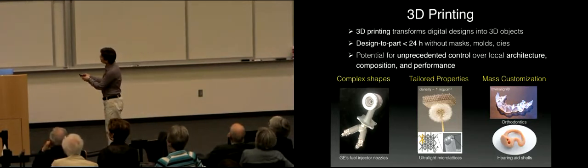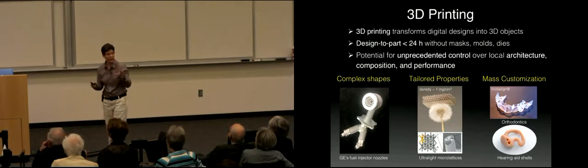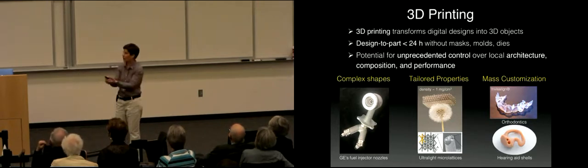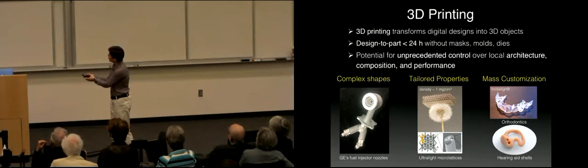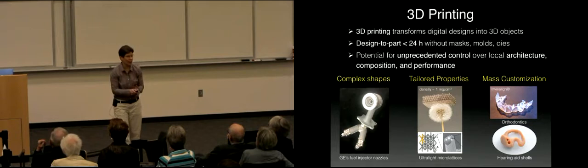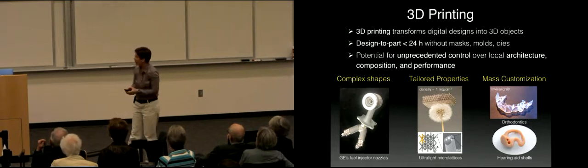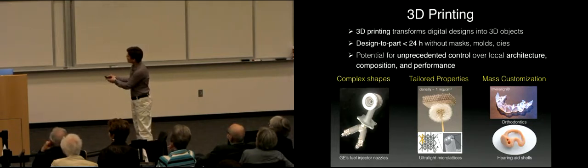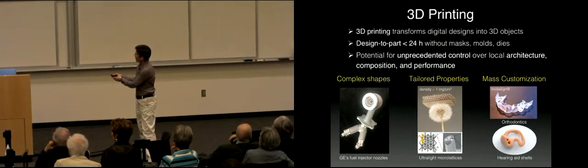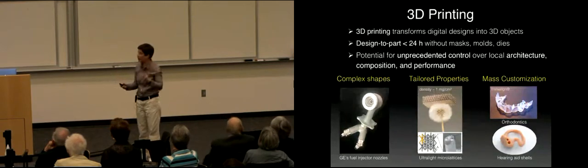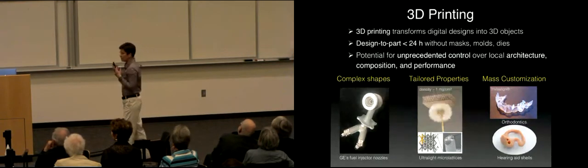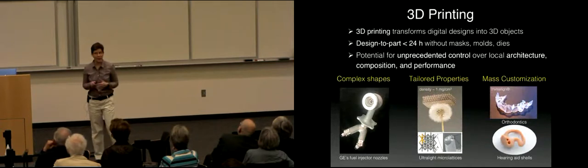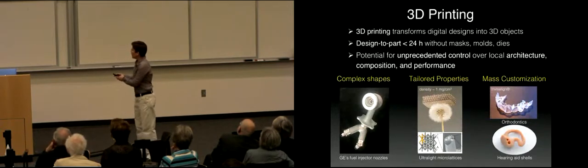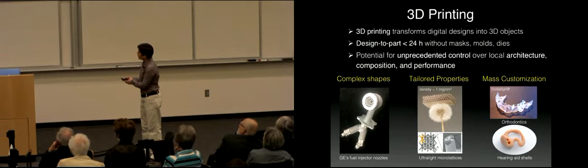And it was printed by first printing a polymer structure, coating that structure with metal, eliminating the polymer to leave hollow channels behind. It's 1,000 times less dense than water, and water's pretty low density. And so you can see it sitting on top of this dandelion. It can support it easily without crushing, if you will, because it's so light. And this has remarkable mechanical properties, exceptional stiffness, and very high resilience.